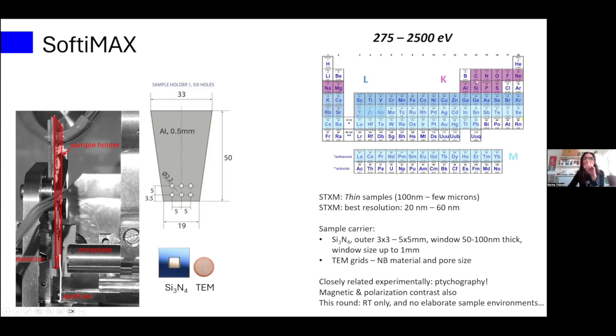which also means that if you want to combine edges, right? So if you want to combine something that is at the lower energy side with something that is at the higher energy side, you might need to make more than one sample, right? Because otherwise you might not either get enough contrast, or if you have very thick samples in the low energies, you might not get through.